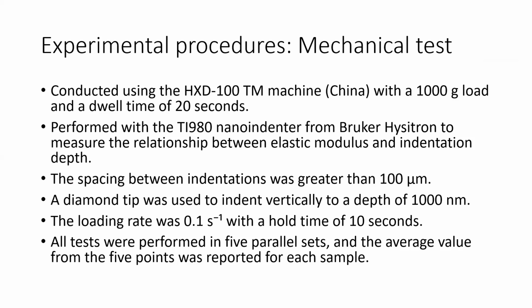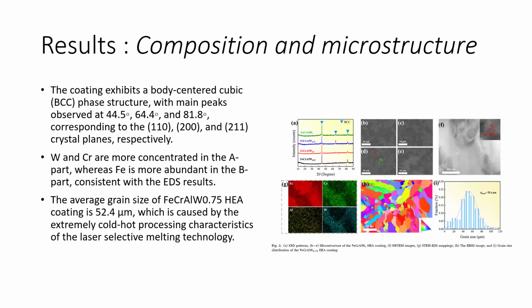The loading rate was 0.1 per second with a hold time of 10 seconds. All tests were performed in 5 parallel sets, and the average value from these points was reported for each sample.